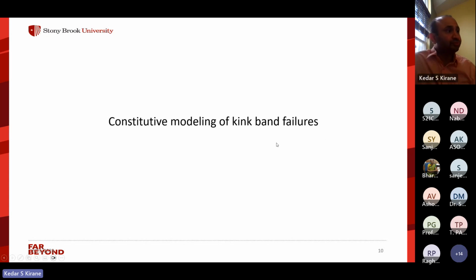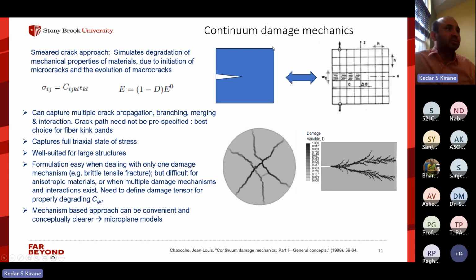So today I will talk about a model that we have developed recently to capture these kink band failures in composites. The approach that we adopted is continuum damage mechanics. Now in literature, you will find many models to predict fracture. There is, of course, starting with the basic, the cohesive crack model. There is XFEM, the extended finite element method. Of course, there is damage mechanics, continuum damage mechanics that we have chosen. There is the phase field model and so on. But each one has its own pros and cons. But as far as the compressive failure of composites by kink band formation goes, the damage mechanics approach has been probably the only effective way of modeling it.